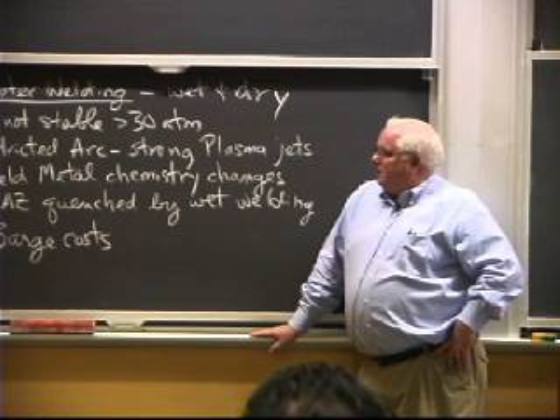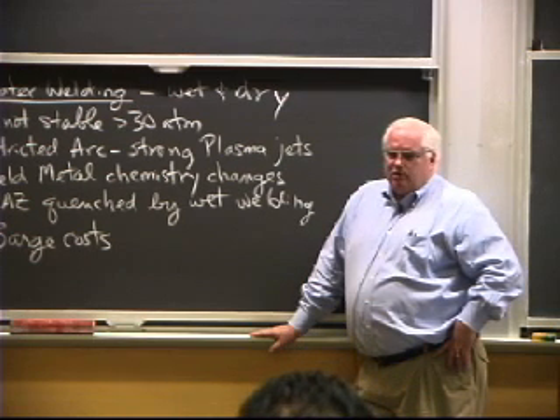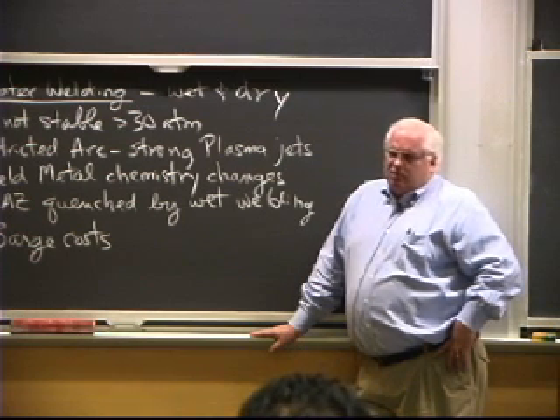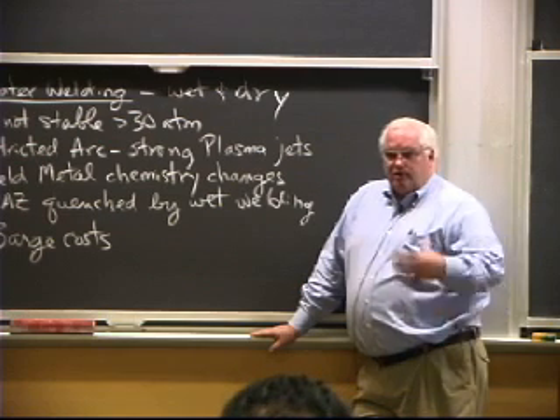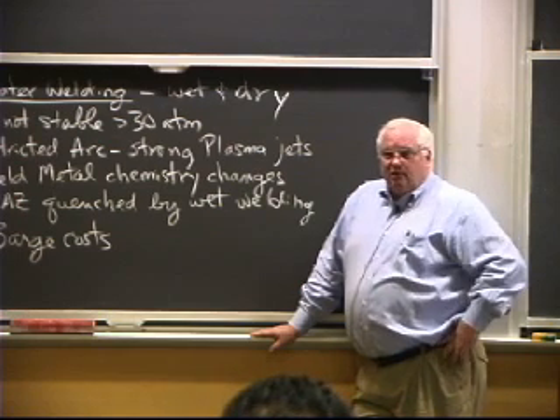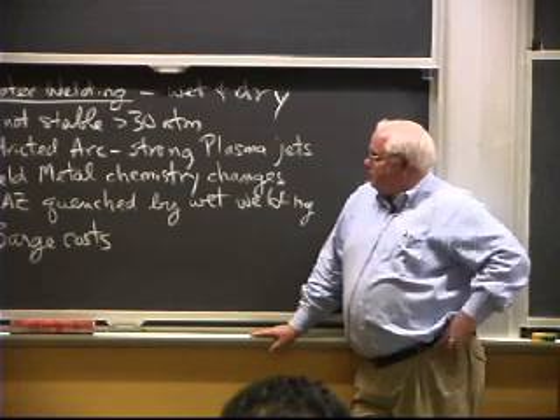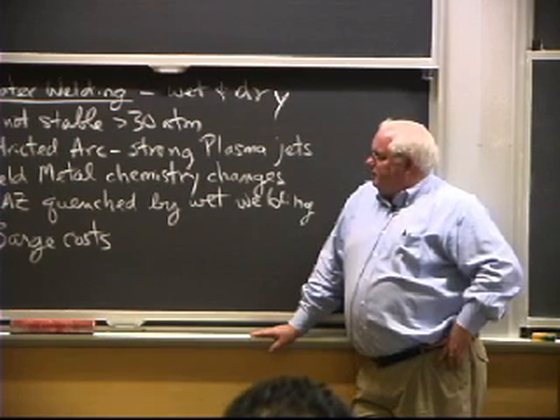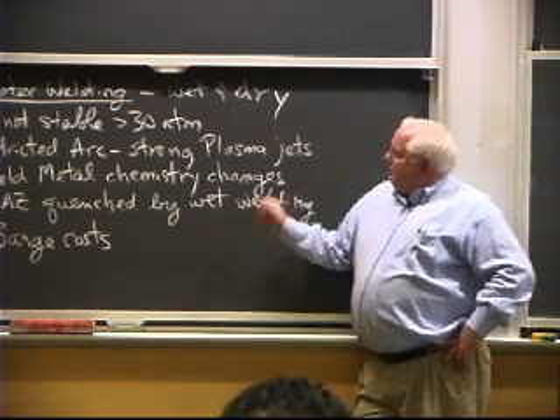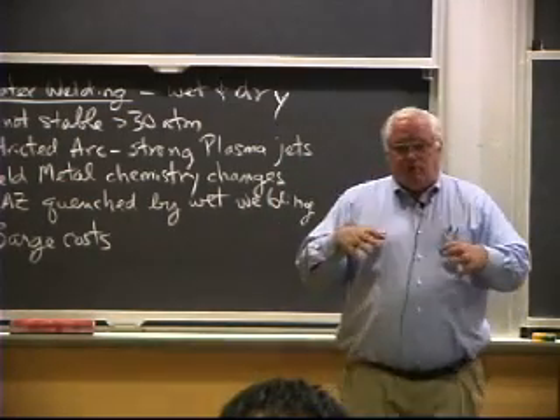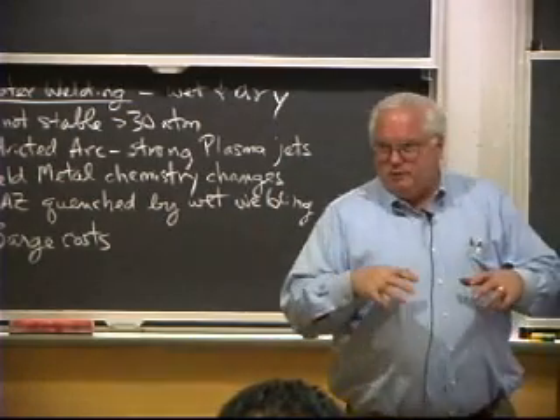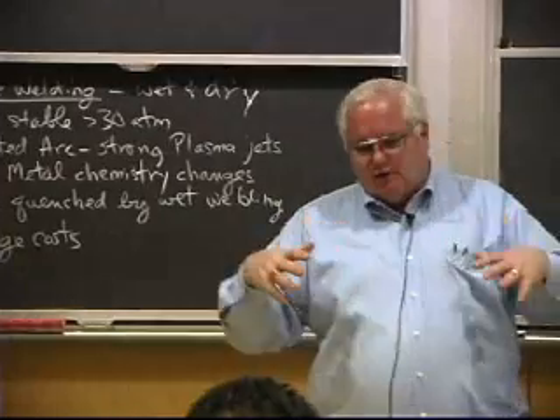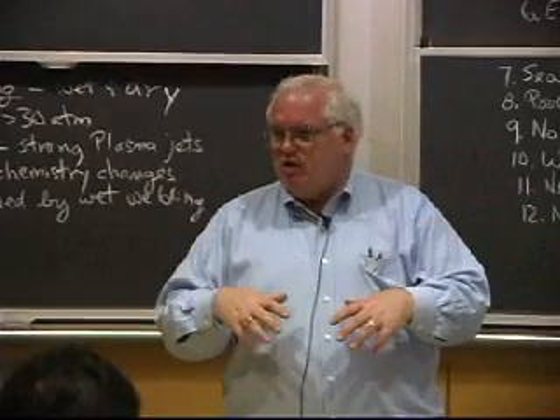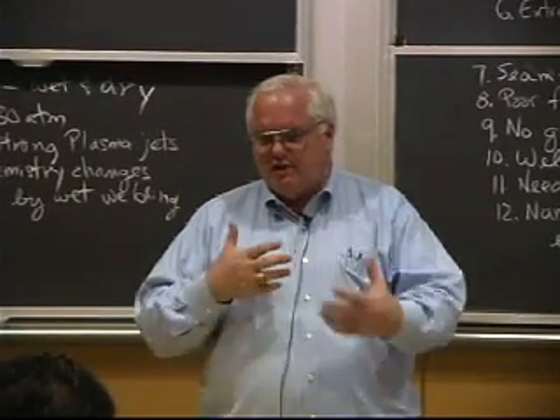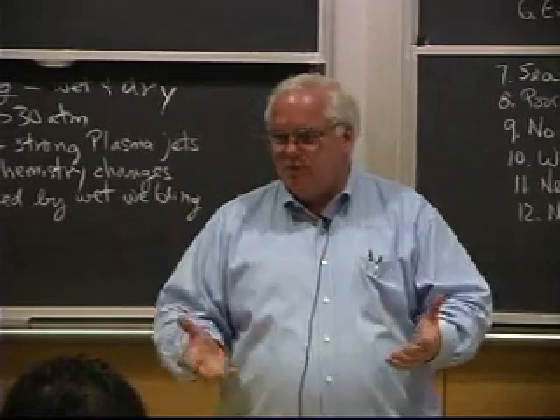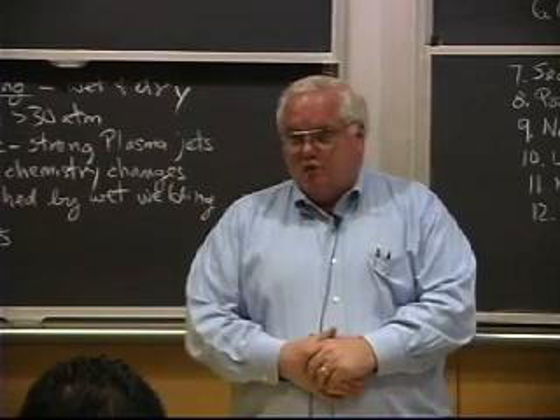But a good-sized jack-up rig can rent for 75 or 100 million a year, so that's a third of $1 million a day just for the rental costs. Okay, now the rental costs include some of the operating people too, but nonetheless, the weld metal chemistry changes because I got a higher pressure. And in a steel weld, which is what you're going to be welding most of the time, it turns out higher pressure means that I got more CO gas. And the CO gas has an exchange reaction with the weld pool, with the carbon in the weld pool, and you're going to get more recovery of carbon.